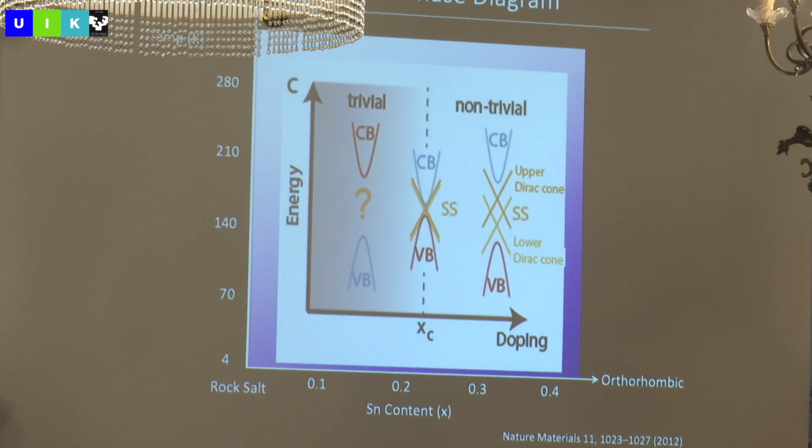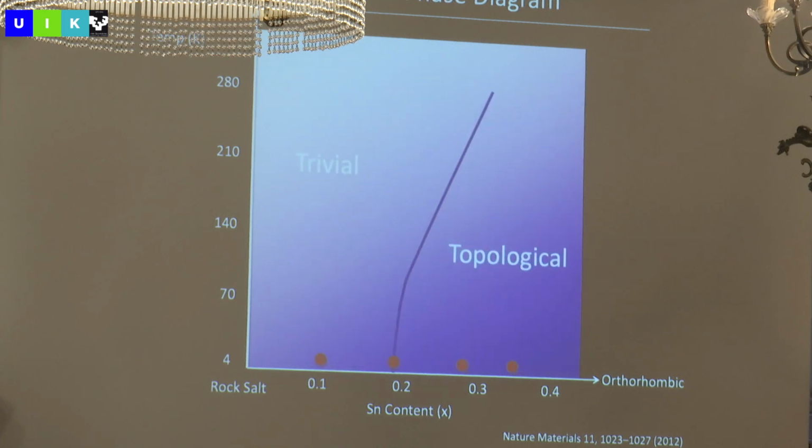So you can use Landau level spectroscopy to track what the surface states do as you go through this phase transition. You remember the bulk band gap has to close and reopen. When the bulk band gap closes, these surface states actually get crushed together, like in this fashion. More interestingly, remember the surface state penetration depth right at this critical point should go to infinity. We should see evidence of that in our data. So let's see what happens.